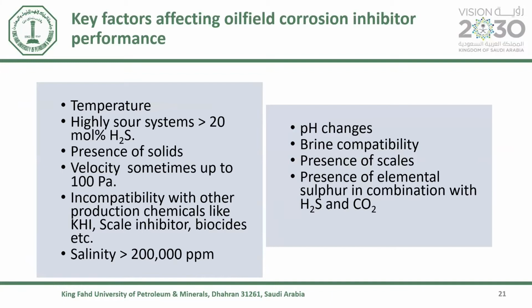So there are a lot of factors that affect the performance of corrosion inhibitor in a typical oil downhole tubing or transportation pipe. For the downhole wells, we know temperature is very critical. Sometimes the temperature can go up to 300 Fahrenheit, and sometimes more, especially when you are dealing with deeper wells. We have very high sour systems, greater than 20% H2S. So this will affect the performance of corrosion inhibitor.